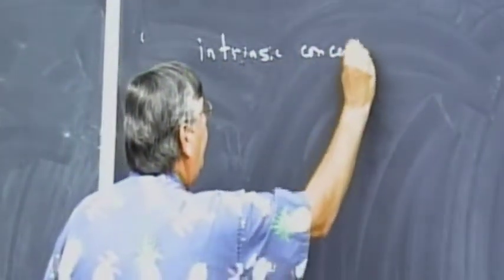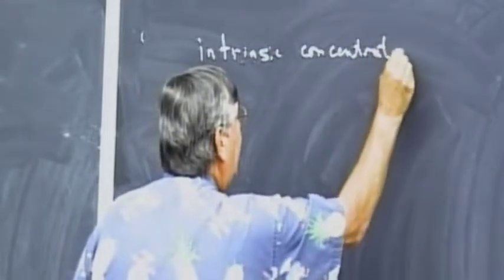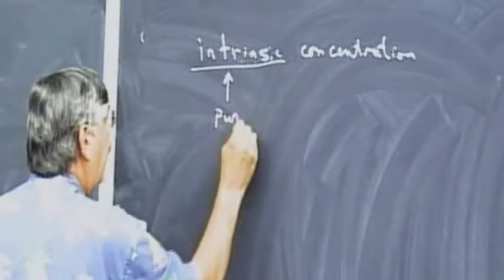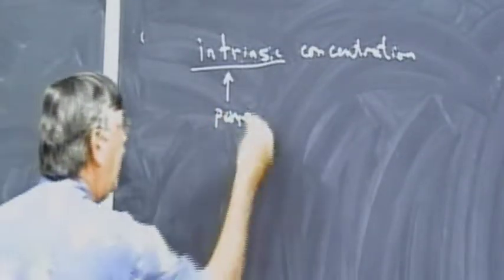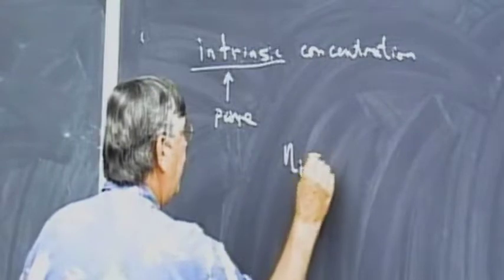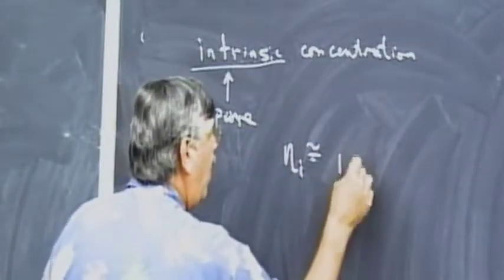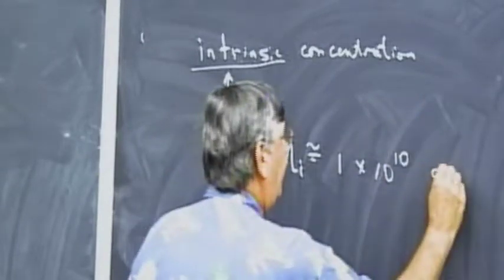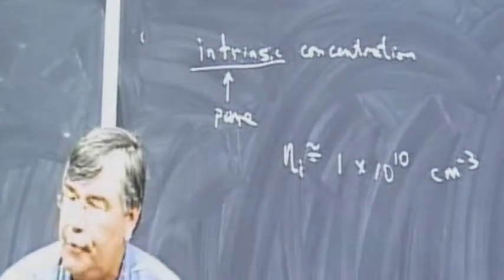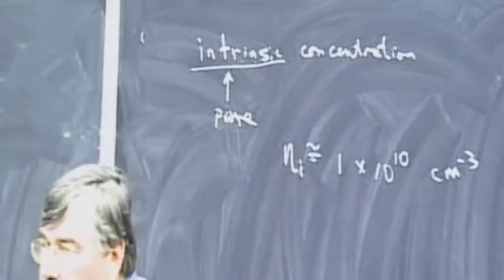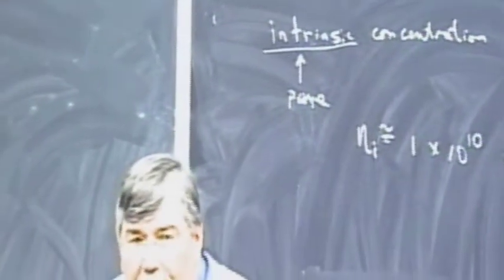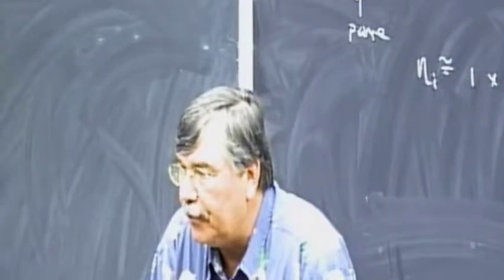concentration. So in practice, we don't very often have so-called intrinsic semiconductors where they're pure, no impurities. But if we did, the concentration would be somewhere on the order of 1 times 10 to the 10th free electrons per cubic centimeter. For reasons known only to the history, we use the old CGS system when we talk about device physics. Instead of the MKS meters, kilograms and stuff, we use centimeters and that other stuff.